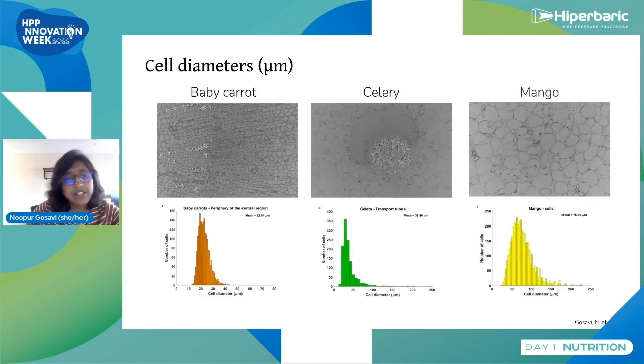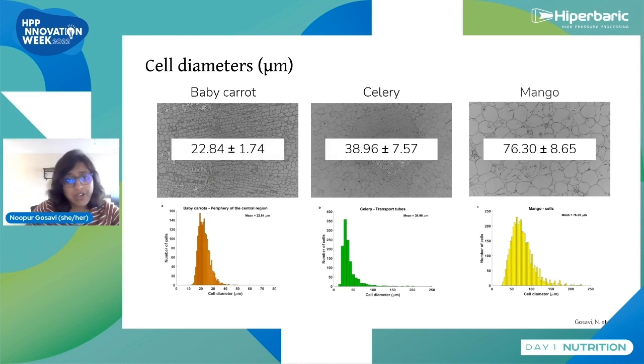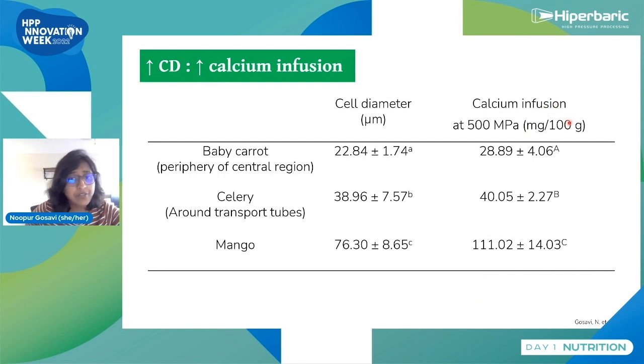So what we did is we looked at these specific points where the calcium was and used these images to quantify the microstructure. So the numbers we got were these. Now, if you look at the amount of calcium that was infused for these food matrices at these different cell diameters, you'll see that there's a strong correlation. Increasing cell diameter led to increased infusion. So it is very important to know that this is a correlation and not the only cause.